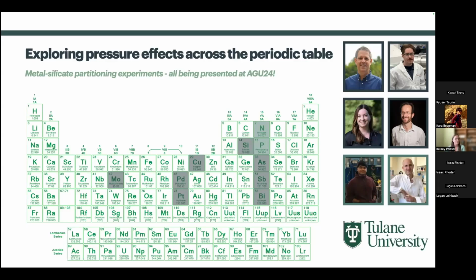Now we're seeing that there's potentially a correlation with this specific group of elements on the periodic table, the pnictogen elements. Seeing this pattern helps identify why there might be a change with pressure, and it might have something to do with these elements and their bonding structures specifically. I want to call out Akanshu. He's the graduate student leading the work for the nitrogen and phosphorus, and he's going to be presenting our results from both multi-anvil experiments as well as diamond anvil cell experiments at AGU this fall.